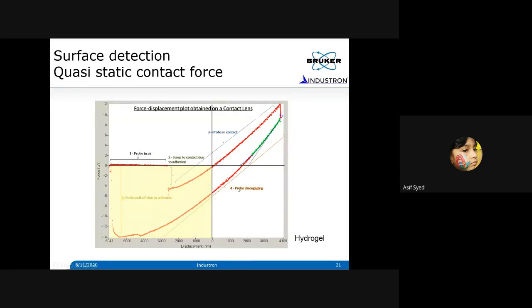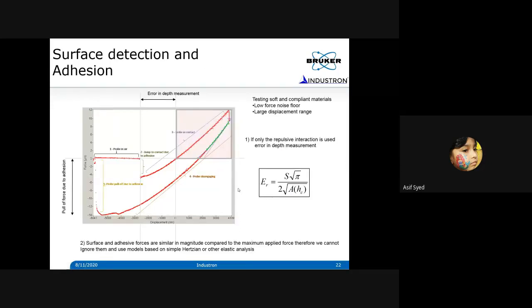The second part is, if you look at this curve, that's what I'm clearly showing over here, and when the probe jumps to make contact, or the material jumps to make contact with the probe, it happens at this point. And then normally what we say is this is the zero point where we start to see the repulsive interaction, the positive force, and we define that as the zero point. And the probe has already penetrated into the sample almost 2,800 nanometers, 2.8 microns in this particular case. So this much error in depth measurement is there in your measurement. So whatever property you are going to measure may not be accurate.